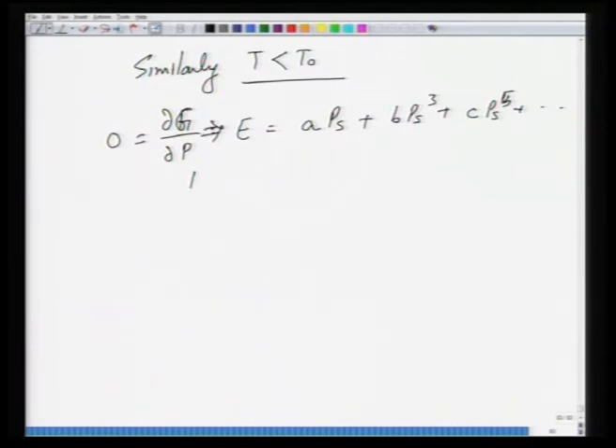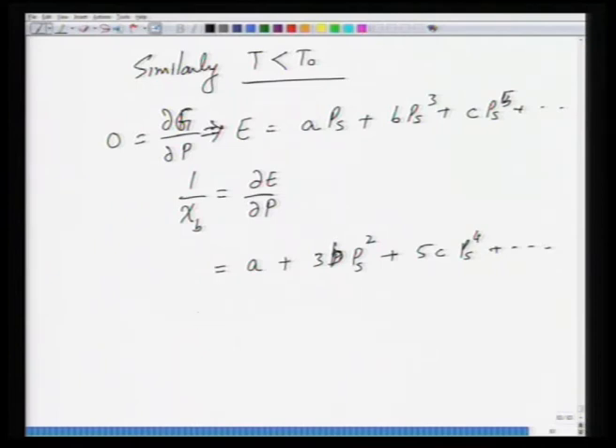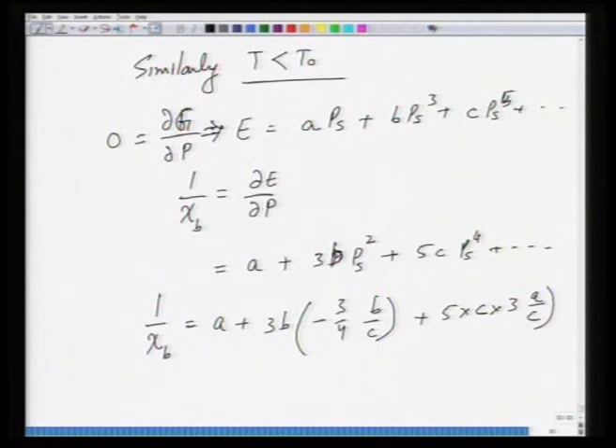So 1 over chi B, which is the susceptibility in the low temperature regime, is equal to del E by del P, and this can be written as A plus 3B Ps square plus 5C Ps to the power 4 and so on. So this 1 over chi B, from the expression of Ps, can be written as A plus 3B into minus 3 by 4 of B by C, plus 5 into C into 3 into A by C.